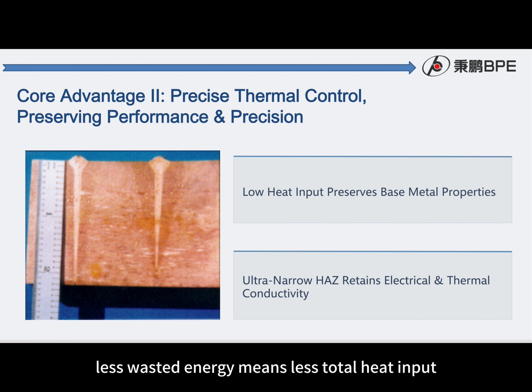Less wasted energy means less total heat input. The overall temperature rise is minimal, giving you an ultra-narrow heat-affected zone. This preserves grain structure, protects conductivity, and keeps thermal distortion so low that post-weld machining is virtually eliminated.